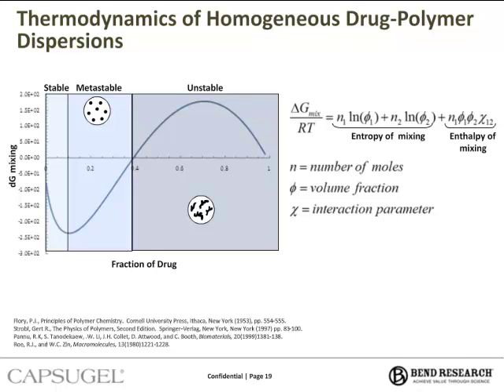So if we look at the right, there's an equation there, and that's for the delta Gibbs energy of mixing. And there's an entropic term and an enthalpic term in this equation. And where the solubility parameters come in is there is something called an interaction parameter denoted as chi. And chi is derived from the solubility parameters. Now, once we have this relationship, we can plug it in, and as you see on the graph on the left, we have the Gibbs energy of mixing versus fraction of drug.